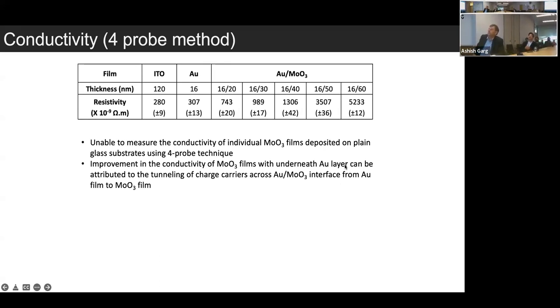In gold, the electrical resistivity seems to be quite high, even higher than the bulk value. Is it because of the dimensional effect? Or is it because it's very thin, and at this thickness it's not a very continuous film? It is semi-continuous. I was expecting that would increase the resistivity.